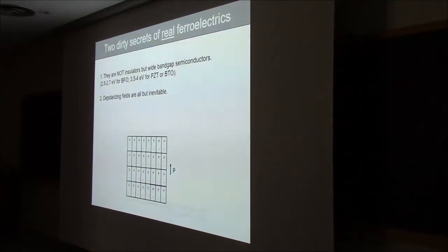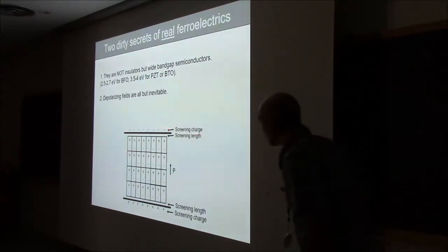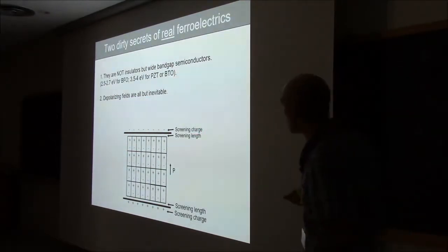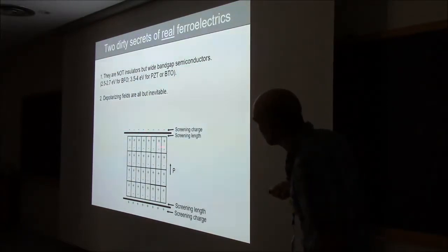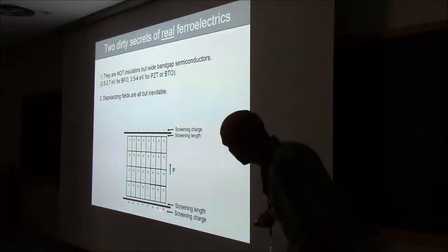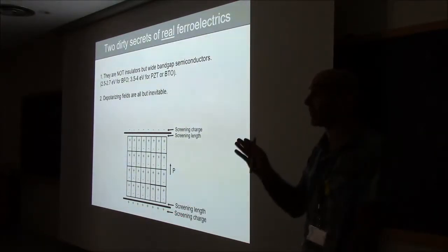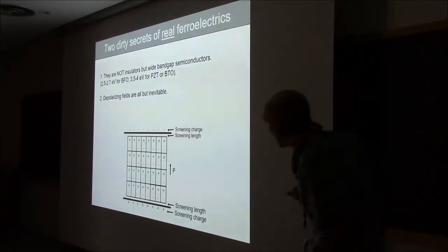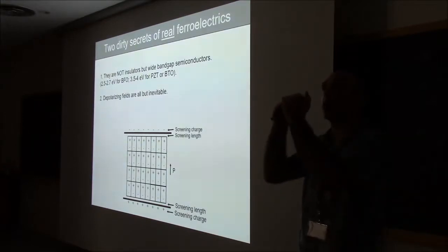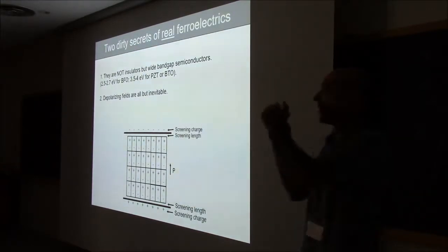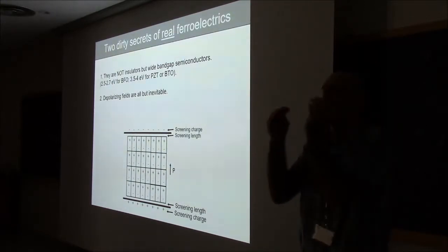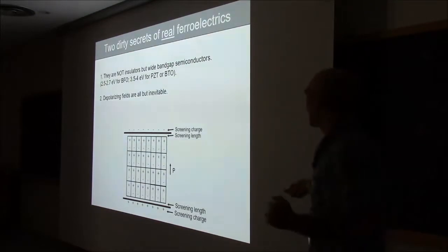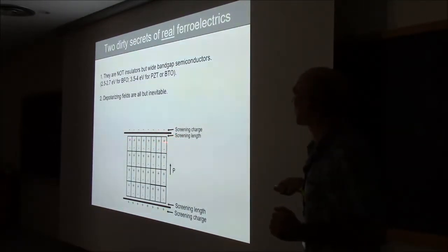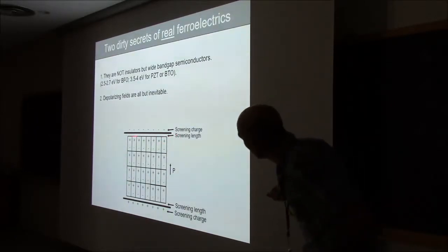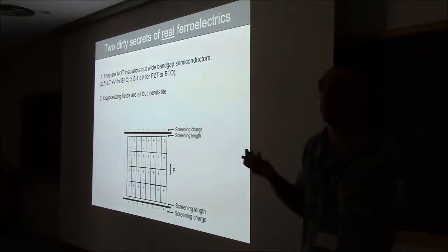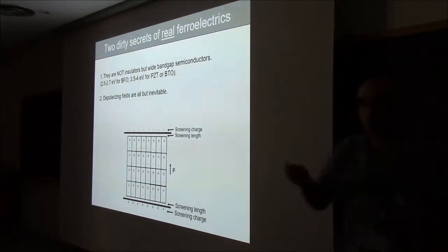Now, in order to screen the depolarizing field, what you do is you put an electrode, and the electrode can freely, very cheaply supply some charge, so you can put some negative charge on the electrode that will compensate the positive charge, and you can put some positive charge here that will compensate the negative charge. The screening, however, is never perfect. Never. It cannot be, because even in a perfect, almost perfect electrode, there's what's called the Thomas-Fermi screening length, which means that there is, if you want, some space in between where the charge of your electrode finishes and the bound charge of your ferroelectric starts. So in this finite amount of space, there's a very big depolarizing effect. Okay? Big or small, but it exists.